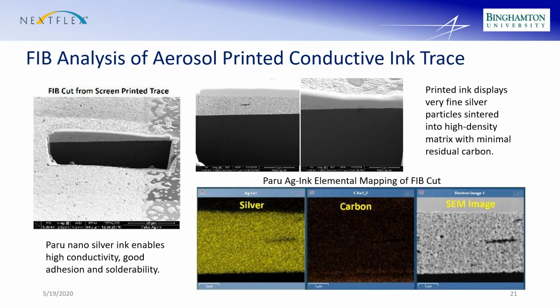All right, and this is a little bit more of a characterization. You can see in this SEM image of a printed line, over here on the right side, that's the overspray. So you see all this stuff here, and there are things that you can do to mitigate the overspray, and we're working with Optomec to do that. And you can see the line, it's not a nice uniform thickness. There is some trailing off on the edge. It goes up to a maximum height, and it'll be that height across the width and then taper down again. So you've got to take that into consideration.